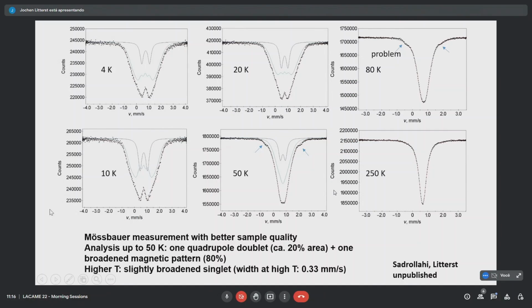We repeated on better samples now Mössbauer experiments after that, and you see, well, it looks very similar to what Bosar had seen, but these big splittings we interpret now after knowing about the muon experiments that must be magnetic. We have an analysis which is composed of a non-magnetic doublet, fast fluctuating, and one broadened magnetic pattern. Now at high temperatures that were already collapsed to a broad singlet level, as you see here.